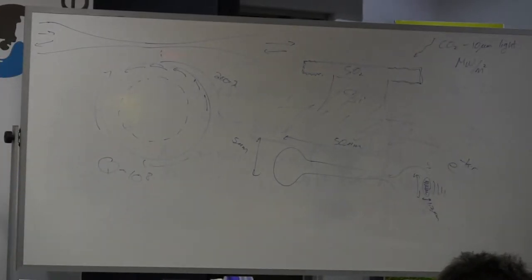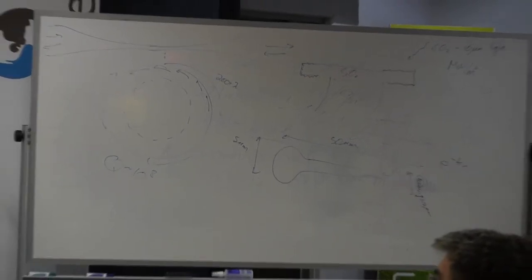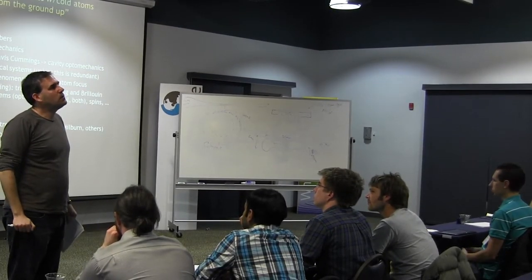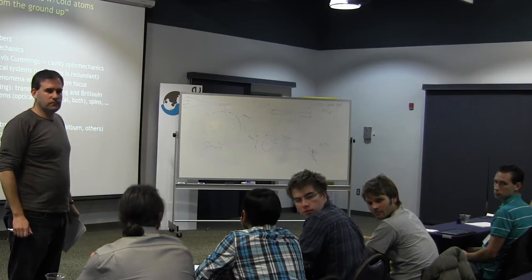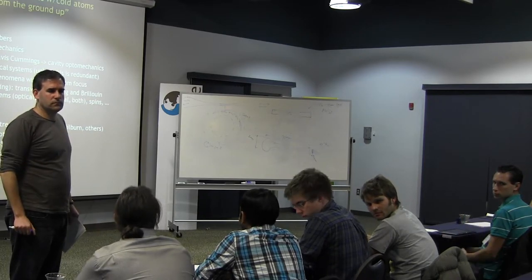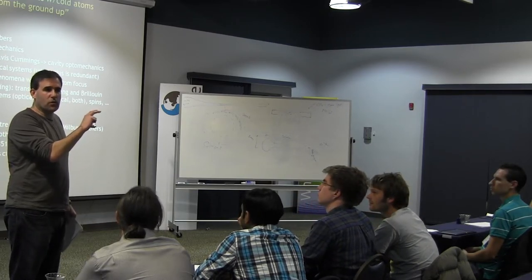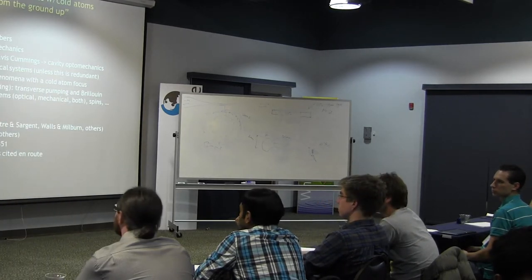How much tapering do they put in these fibers? Is it probably not as much as you drew here? Oh, it's not at all drawn to scale. So it's really over a long length. Can you reduce the radius by a factor of 2 or something like that? Do you know? I think it's just a few microns. It's something like 6 centimeters of pull. Right. So the tapered region is something like 6 centimeters, and the thinnest region is probably 2 microns wide. So you go from having like a 100 micron or so core down to like 2. Oh wow. It's really fragile. Yeah. But it's much stronger than you would like.